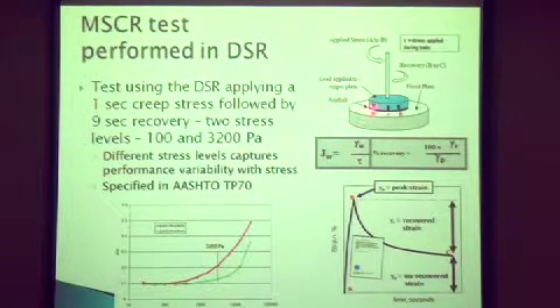During the test, we start at this point A. The rheometer moves to a point B, and we put a load on the rheometer, take the load off, and it comes back to a point. What's happening? Here's the load going on at point A, up to point B, you take the load off, it recovers to point C. That's what is going on in the test.